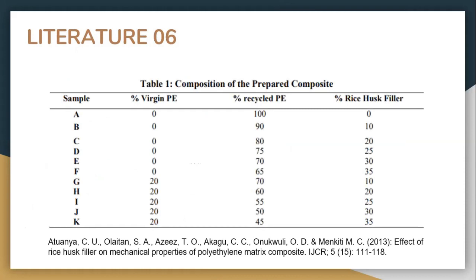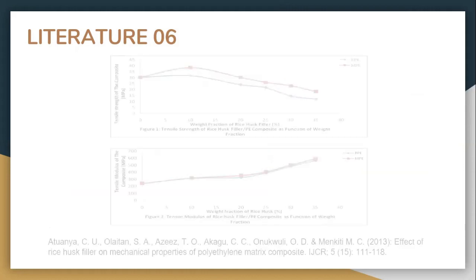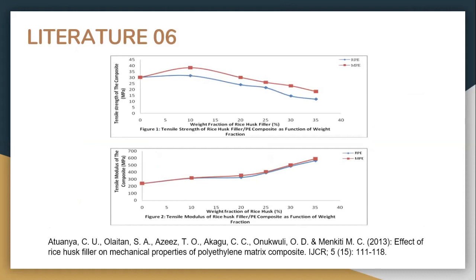In a study of Atwania, varying amounts of rice husk filler loadings 10%, 20%, 25%, 30%, and 35% weight fraction were added to recycled low-density polyethylene or RPE mixed with a 20% weight fraction of virgin polyethylene or MPE composites. The samples were then cut into specific dimensions for testing. Through the use of the universal testing machine, it was observed that there was a gradual increase of tensile strength at around 10% weight fraction addition, but experienced a sudden decrease with further percentage additions.